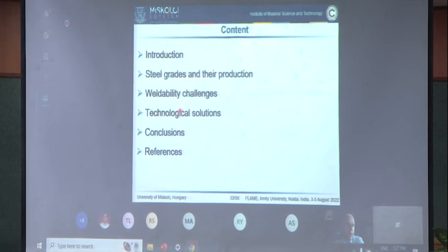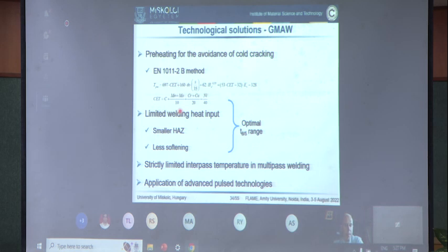Now, after seeing the challenges in weldability and welding, let's see how we can handle these problems. In conventional gas metal arc welding, of course, we need to use preheating, especially for quenched and tempered steel. For preheating, we use different kinds of methods. We need to use a limited welding heat input, and we need to consider the optimal t8/5 cooling time range of the steel producer.